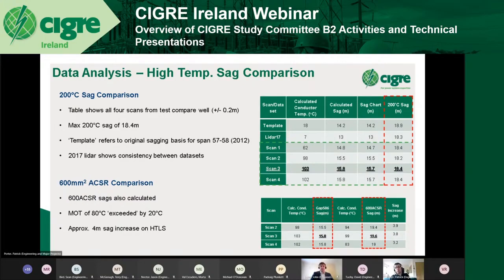If we focus on scans 1 to 4 and consider them as one data set, an MOT SAG of 18.2 meters versus 18.4 for the other 3. So that shows good correlation across that. Then considering the 2017 LiDAR, which was a completely independent or separate data set under much different loading conditions, ambient conditions, etc., we got 18.3 when we projected that out to 200 degrees, so that shows good consistency across all.